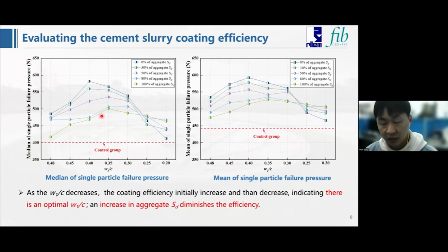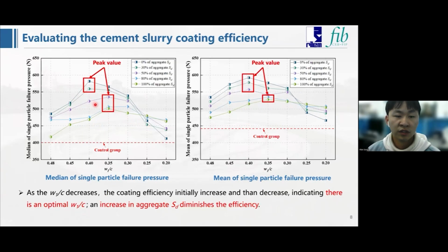Firstly, we conducted the aggregate coating test to evaluate the effect of different aggregate SD and stage 1 mixing water to cement ratio of slurry on the coating efficiency. As the result shows, as the water to cement ratio decreases, the coating efficiency initially increases and then decreases, indicating there is an optimal water to cement ratio. Moreover, an increase in aggregate SD inhibits the efficiency. So why did we get such an experimental result?